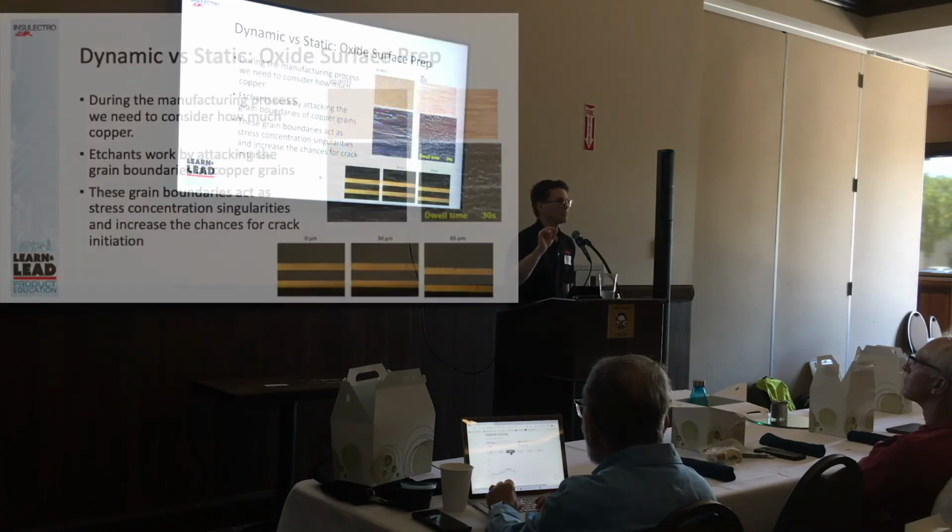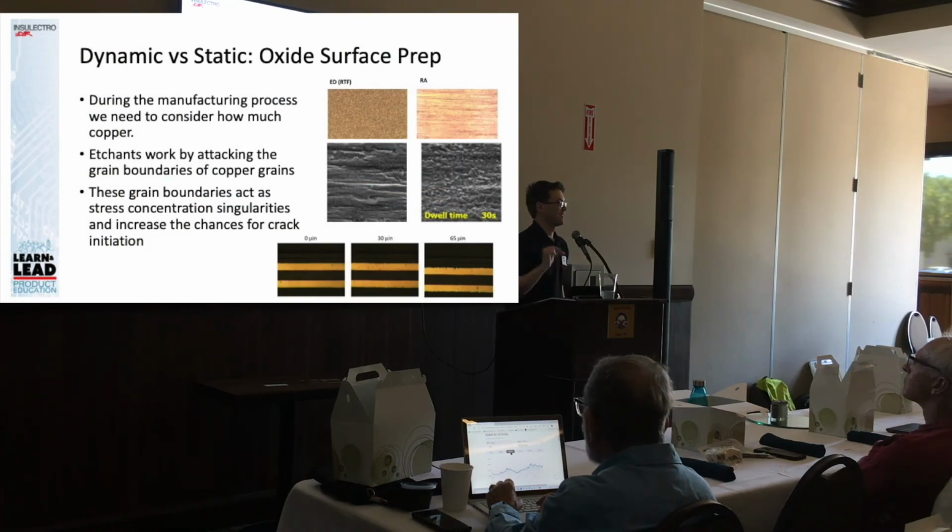The one thing that is often missed is surface preparation during fabrication and how that affects not just our flex performance, but our signal integrity on the rigid side. We remove copper at multiple steps during the fab process. We do it when we first pull the panels out of the box, when they start going through interlayer pre-clean. By the time we get to alternative oxide, we can have etched off quite a bit of copper from these